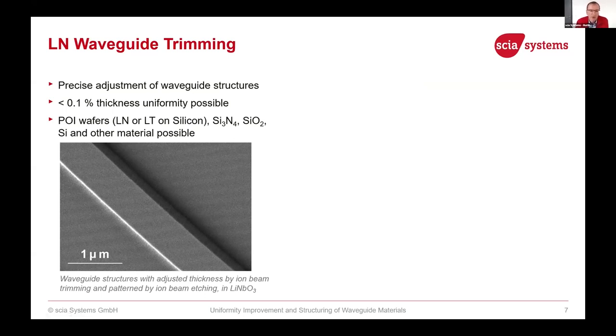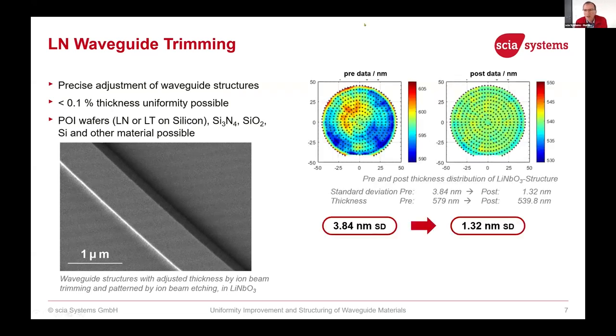This can be applied for POI wafers, so lithium niobate or lithium tantalate on insulator, for silicon nitride films, for silicon oxide films, or silicon films on silicon oxide, so SOI wafers. All these materials can be trimmed. Even other materials are trimmable with that principle. We achieved uniformities of 0.1% and better. Here are some nice examples of lithium niobate trimming.